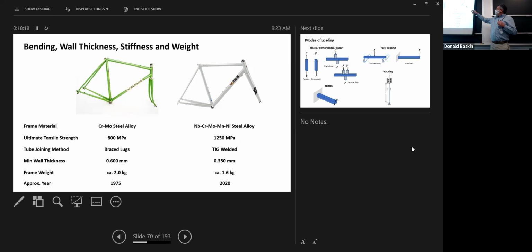If you look at the tubes on the white frame, they're much bigger in diameter than the tubes on the green frame. So you have a combination of larger diameter, thinner wall thickness, which means essentially less volume of material. You're able to do that because the material is stronger and because the tubes are bigger diameter. So this is what I call strengthening by geometry. And of course, there's material strengthening here too, because the white frame is made out of much stronger material. But this is a demonstration of what you can achieve in, what is that, 50 years or 45 years? Okay, 45 years of development.